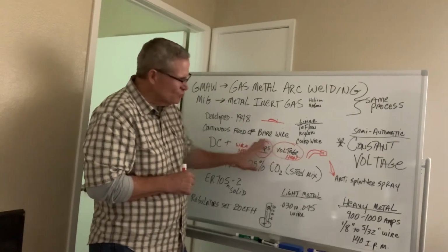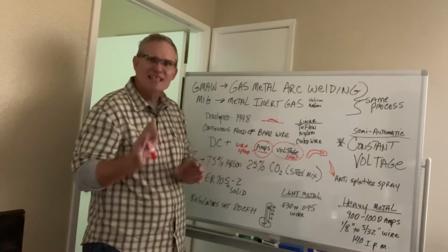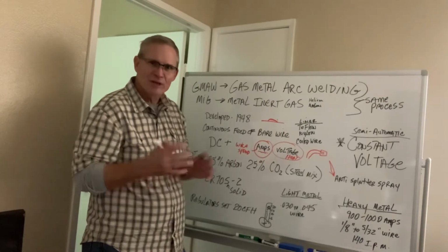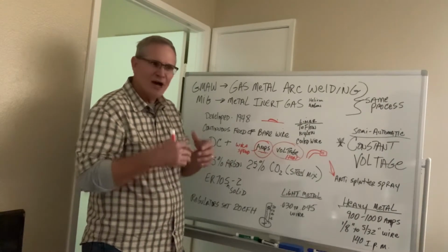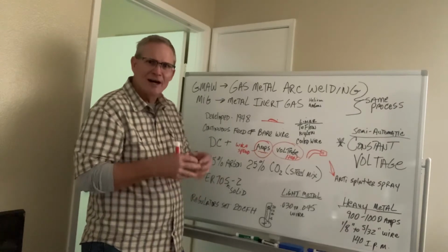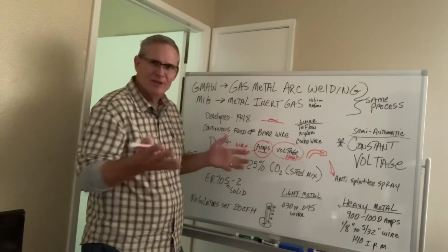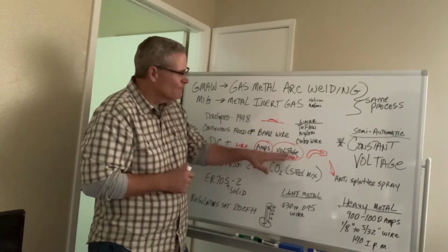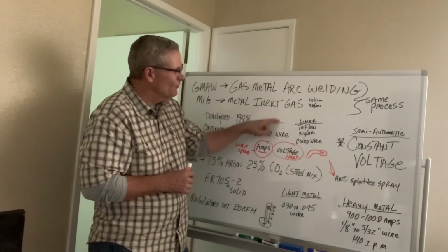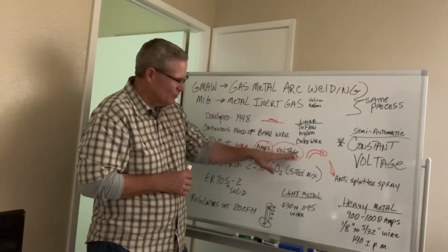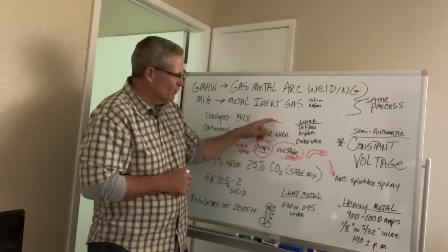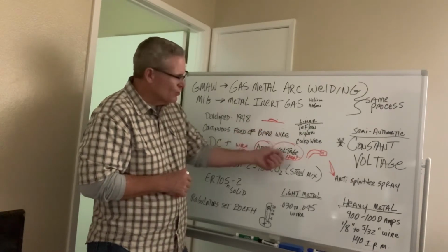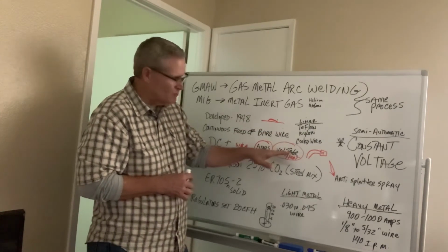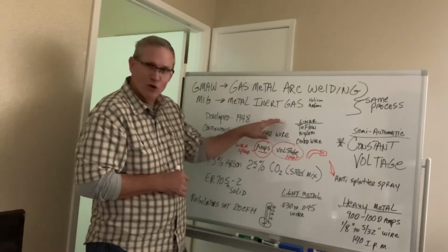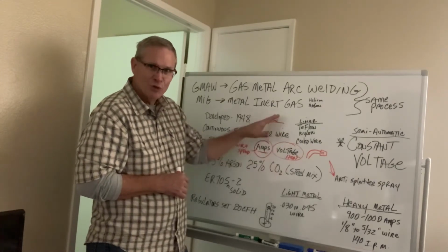When you get these two dialed in properly, it sounds like bacon frying. You're not over penetrating. Let me give you some of the signs of it, okay? Voltage, I just demonstrated to you. If it's real cold, you're going to have to increase the voltage. Again, if you're burning through the material, you're going to have to back off on the voltage because you have too much heat in order to get the right penetration value with it.